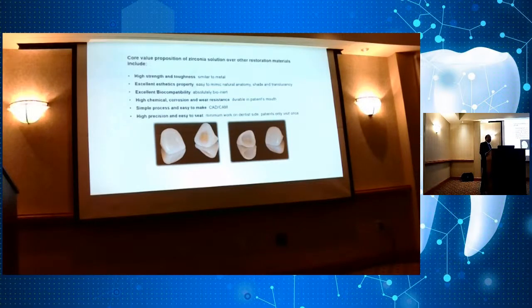Lithium disilicate is the same temperature, 1,000 degrees? Yeah. So you have to probably sandblast the glaze off and then reseal it and then reglaze. Guaranteed it'll work. Yes, sir. So you're saying like I have a full contour zirconia, and after I glaze it, there's a hairline fracture. Yeah. So after that, I can go back. Yes, you can. So depending on your glaze temperature, if it's below the glaze temperature, raise the temperature to 1,000 degrees Celsius. Hold it in air for 5 minutes, and you will see the crack disappear.